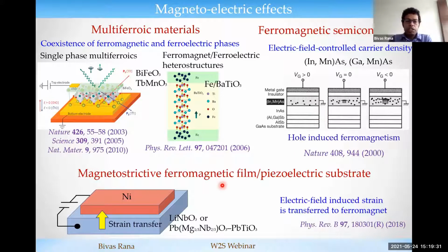And the third option is to put a ferromagnetic film on top of a piezoelectric substrate. So when you apply an electric field across a piezoelectric substrate, it induces strain. It may be compressive or tensile strain, and that is transferred to the adjacent ferromagnetic layer. And through magnetostriction of the ferromagnetic layer, you can tune the magnetic property of the system.